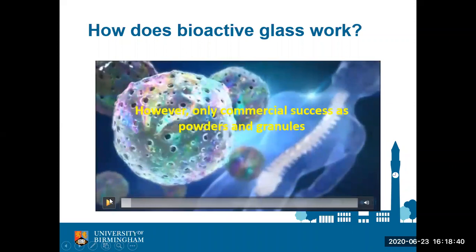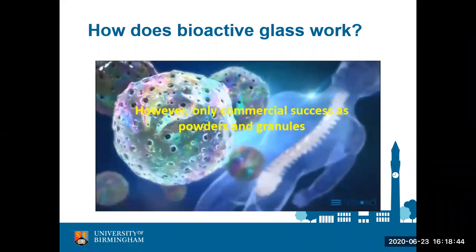As you saw in the video, when you put in the bioactive glasses, a reaction starts and forms a hydroxyapatite surface, which stops it from being rejected. Over time, osteoblasts come in and build new bone on top of the bioactive glasses, and osteoclasts come in and remodel it into the appropriate structure and properties.